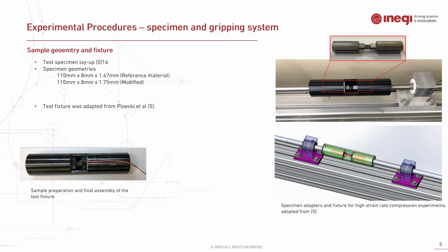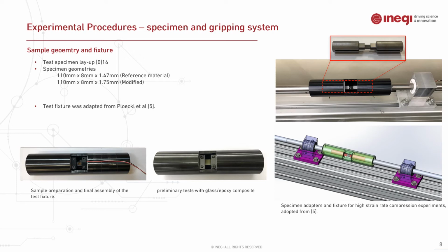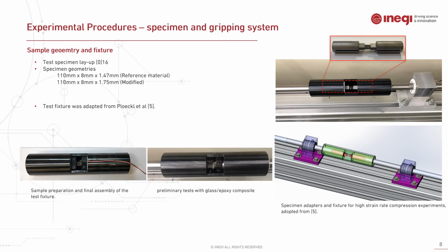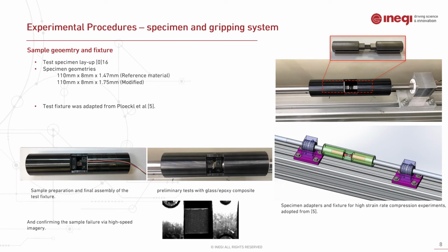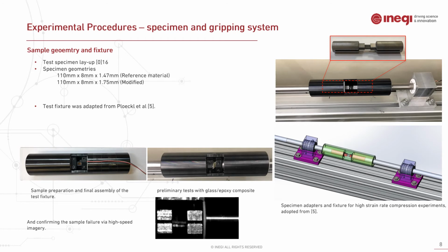But before that, we performed several preliminary experiments using glass epoxy composite material to confirm the validity of the experiment. And you can see the post-failure of the specimen subjected to an impact of 7 meters per second. And over here you can see the record from the high-speed camera and also from the cross-section, which actually confirms the validity of the experiments, and we are sure that the failure occurs within the first stress pulse.